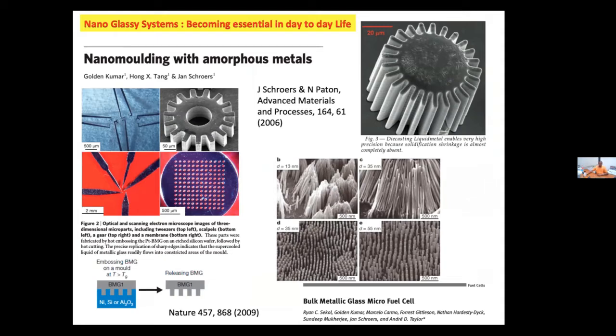This has already been used for many years, you see. The main advantage is that when you take this liquid metallic glass and pour it into molds, and then when it solidifies, the change in density is almost negligible. So that's why when you get the final product, there is not much difference in the structure, and you don't need to do further polishing of the material or the product.